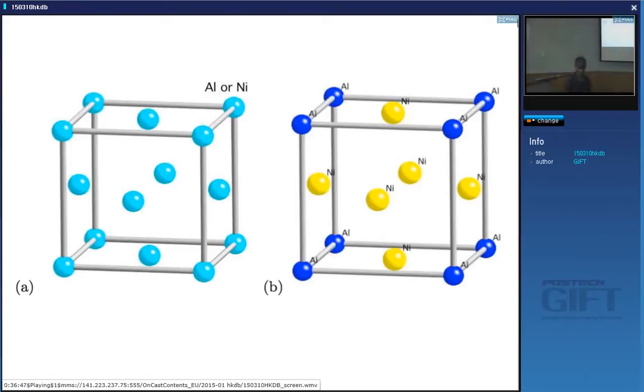Okay? So this was discovered maybe 1950 in Britain, where you try and match the precipitate with the matrix with a very low interfacial energy because they're both cubic, their lattice parameters are not very different, and they meet edge to edge because it's just an ordering reaction. The actual system is more complicated. It's not just Ni3Al, but there will be Ni3AlTi and so on because there are many parameters you have to satisfy in order to design a good alloy, not just coarsening.